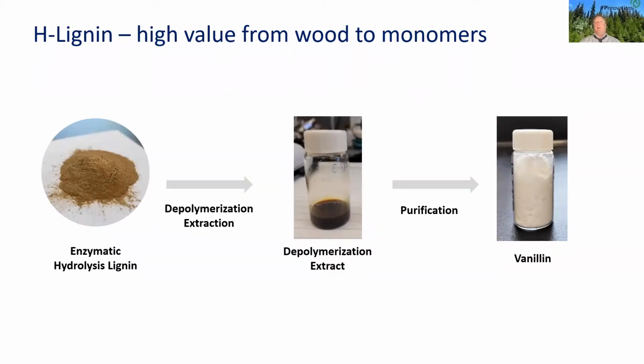As exemplified by this process that was achieved in Pointe-Claire, hydrolysis lignin was brought to a depolymerized form, extracted and purified to vanillin at significant yield with a very high purity product. And this could be amenable to many different monomer transformation possibilities for the fine chemicals industry.